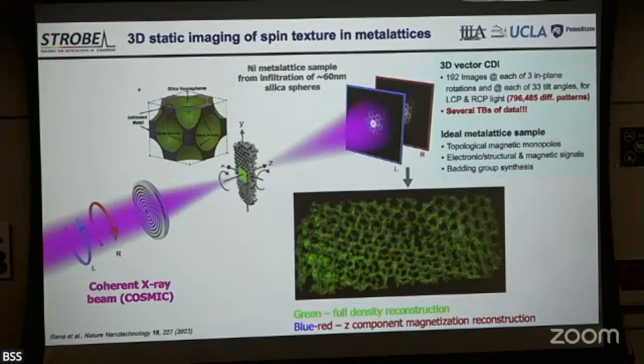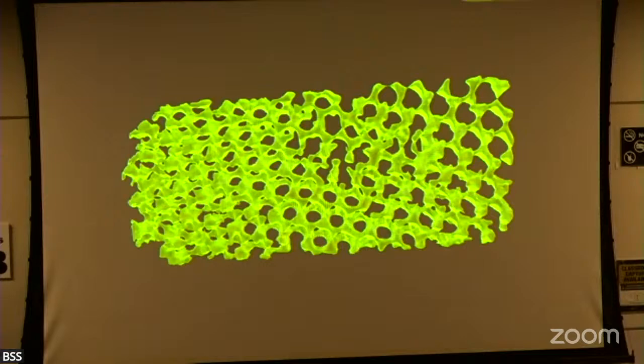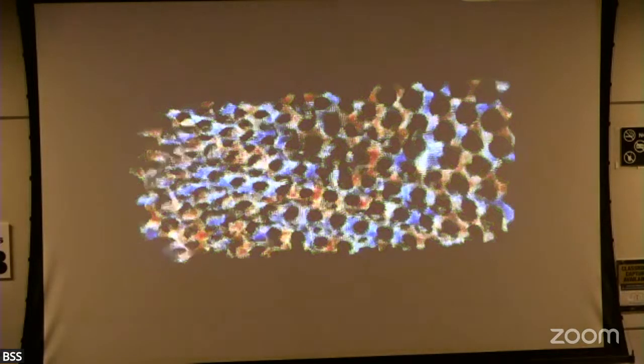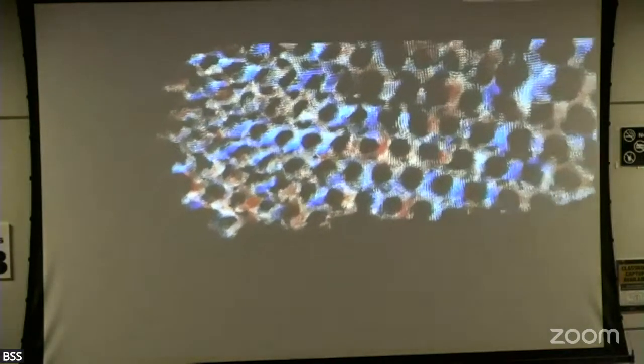But the nice thing about this sample is it has electronic structure. So it's a nickel metal lattice. It's got these little nickel spheres and necks. And so it helps us with the scalar tomographic alignment. So then we know that our vector or 3D spin texture is accurate. And so this is a little movie. You can see, it's not a perfect structure, but it's perfect for our purposes. And you can see that we can see regions with hedgehogs and anti-hedgehogs, or topological monopoles and anti-monopoles.